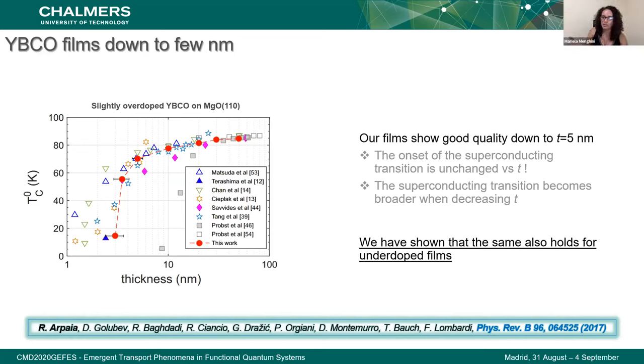But 5 nanometers is how many unit cells, right? It's 4 unit cells. Okay, so we are at the limit. Yes. Below that limit, we see that the superconducting properties start degrading because there is a very strong oxygen out-diffusion. Okay, great.